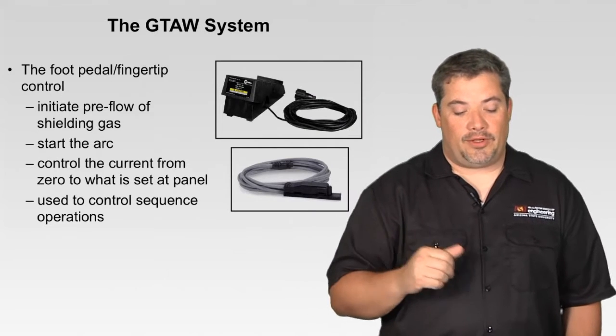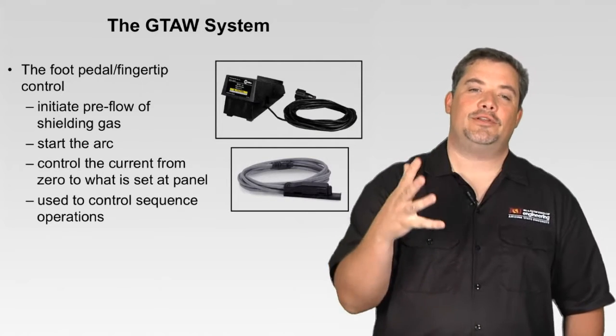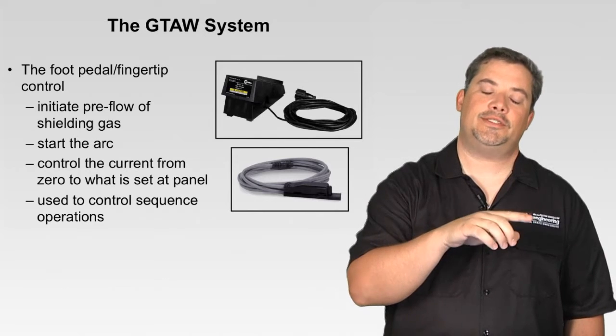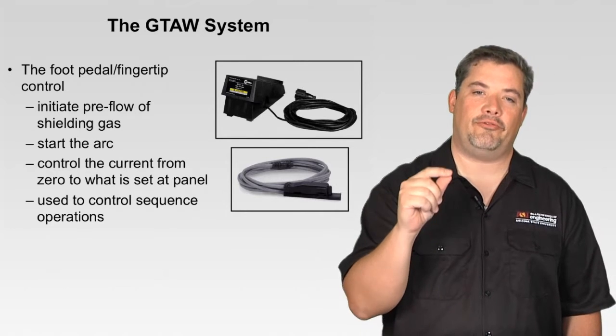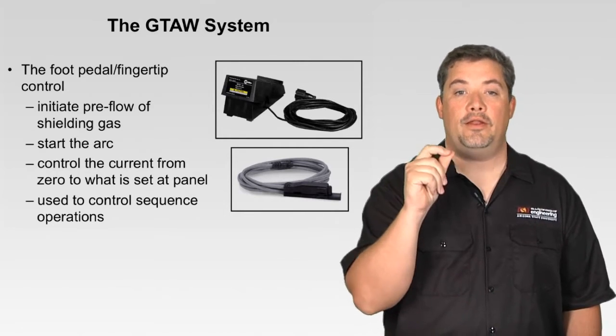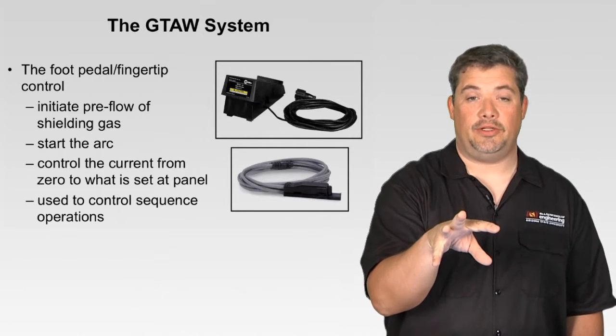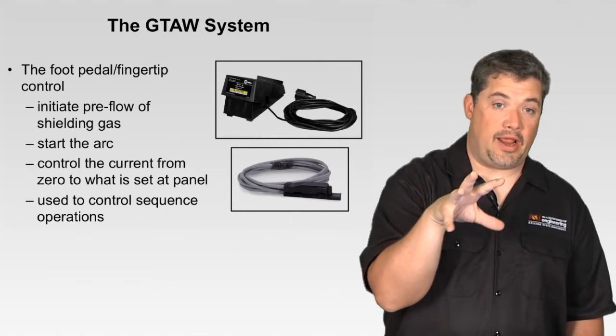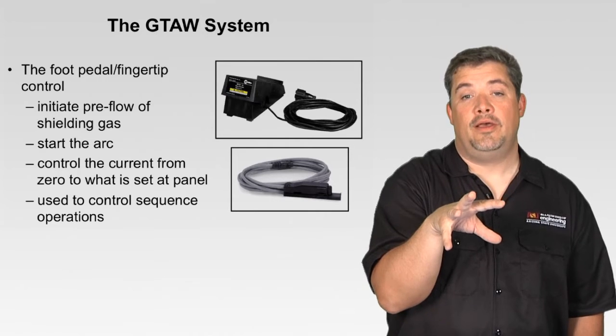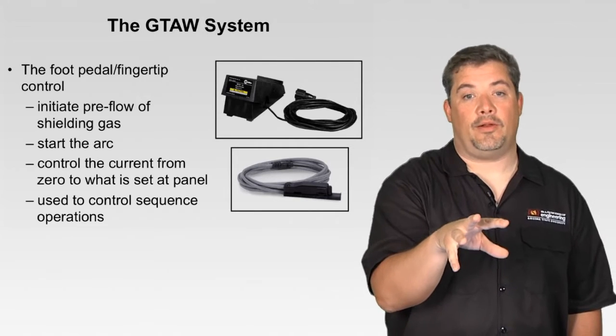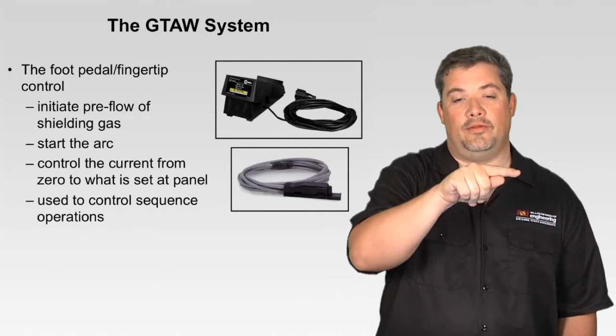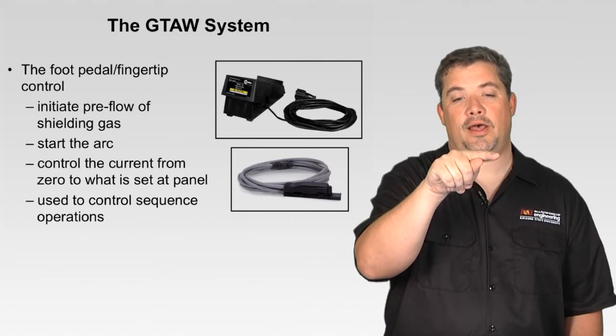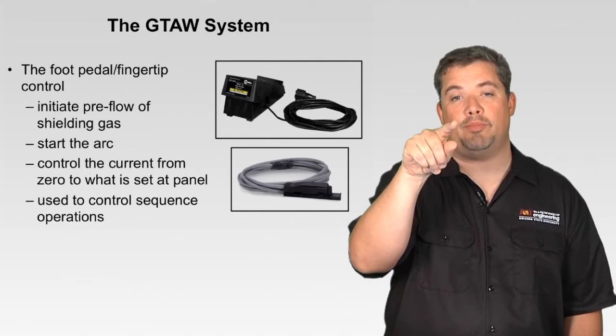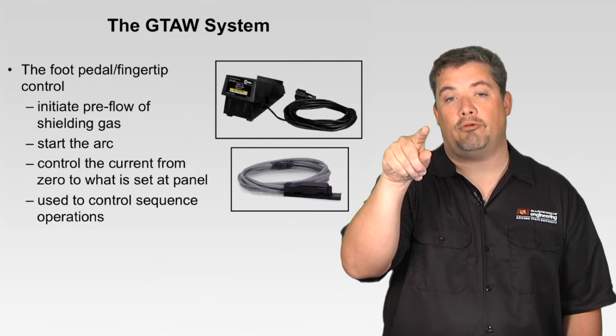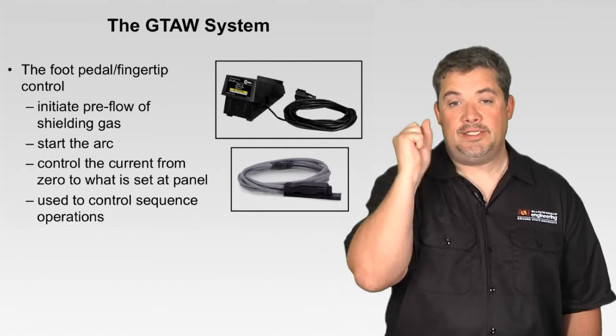So the foot pedal, fingertip control, does a lot of functions for us. When we're TIG welding, there's a sequence of events that occurs. So when I first hit that foot pedal, it'll initiate the gas. It'll turn on the shielding gas. And then it'll want to, and I can change how long it delays, then it will want to start the arc. So hit the foot pedal, gas comes on, we start the arc, we ramp up to welding speed. We get to the end of the weld, we have to crater off to the end of the weld. We can't just instantly shut it off.